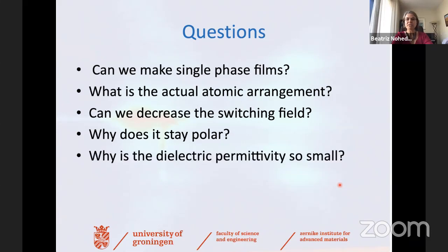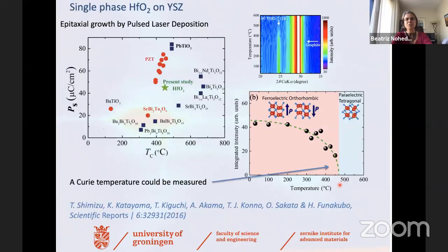One answer to that question could be that the dielectric permittivity of hafnia is much smaller than the permittivity of normal ferroelectrics, maybe one order of magnitude or even two orders of magnitude smaller. And that's why maybe the effect of the depolarization field is not so strong. But then the question is, why is the dielectric permittivity of hafnia so small?